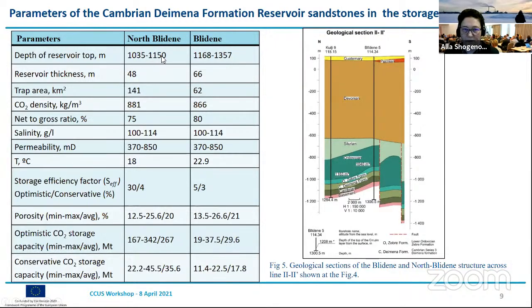The depth in the North Blidina is more than a kilometer, the thickness about 50 meters, so the net to gross ratio is very good. The temperature in our Baltic structures in Latvia is rather low at such depths, about 20 degrees Celsius, but for CO2 storage, it's a good parameter. And we have good average porosity, 20%, and an average optimistic storage capacity of about 267 and conservative about 30 million tons. And conservative about 36, and for the smaller part, 30 optimistic, 18 conservative.